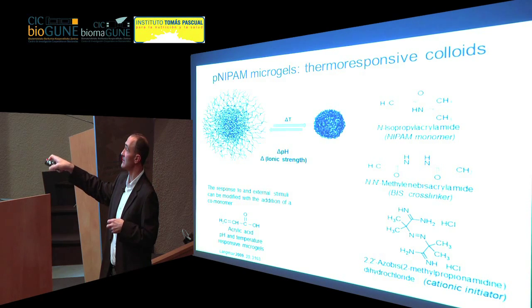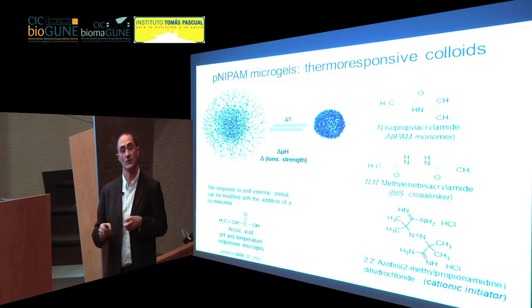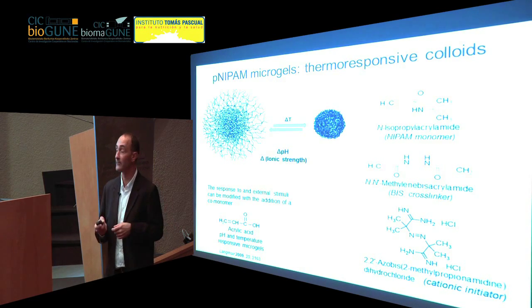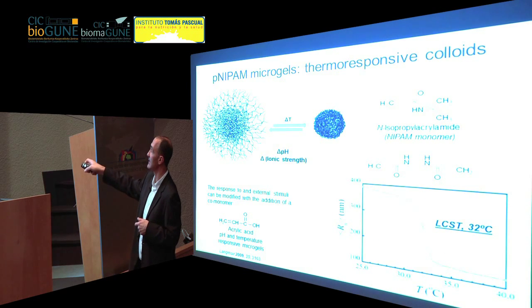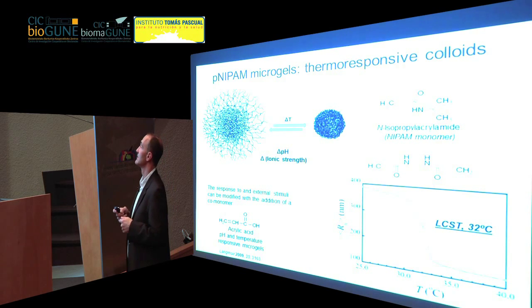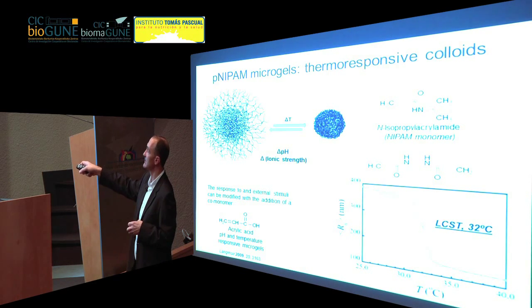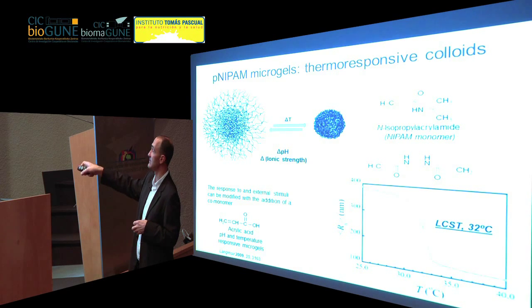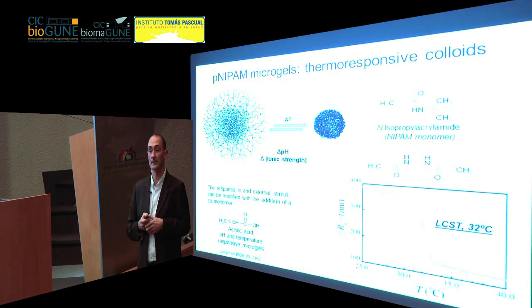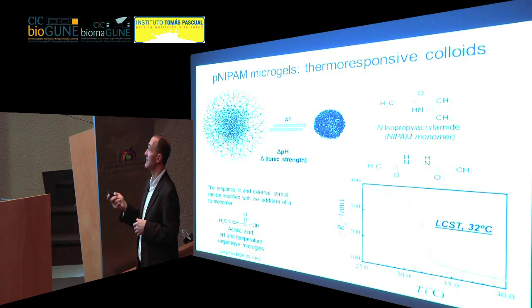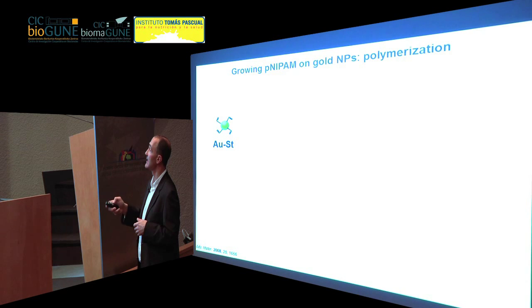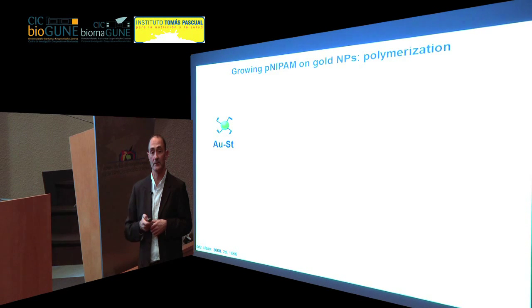You can also change the composition of the polymer with, for example, this acrylic acid group, so that it's also sensitive to pH or to ionic strength. So you can fabricate and tune the composition of the polymer so that these transitions take place by affecting either temperature or pH in solution or other external parameters. What you see typically is something like this. This is the so-called lower critical solution temperature. This is a plot of the size of the particles versus temperature. You see that at around 32 degrees there is a sharp transition, which tells you that the particles become much smaller. So we decided to combine this with our metallic particles, and we designed a process for coating the gold nanoparticles directly with the microgel.